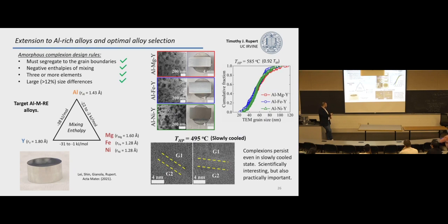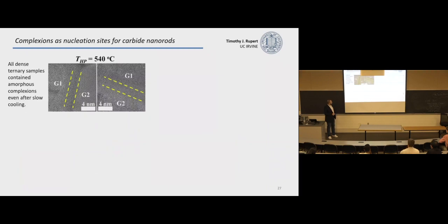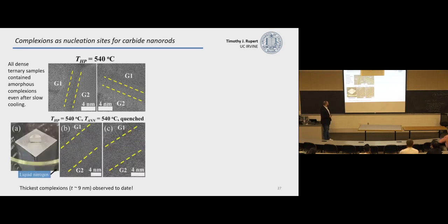We made these bulk samples in a hot press, turned off the hot press, and waited a few hours while it cooled down. These are not quenched at all. These are cooled over multiple hours, and they still have those amorphous intergranular films. So they're very, very stable in these microstructures. This is just showing other examples. All of these ternary alloys have these amorphous grain boundaries. If you redo this experiment where you heat it up and then quench it, you get extremely thick amorphous grain boundaries. So these are about 9 nanometers thick, right?